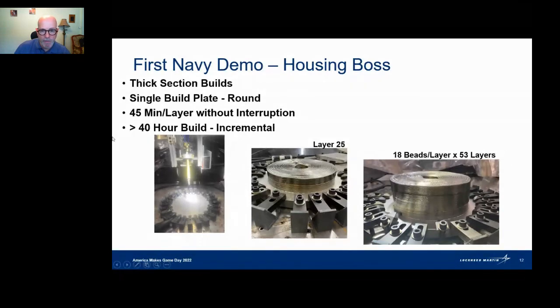The image that you see right here is when we'd gotten up to layer 25, and in the final image you can see it's 53 layers at 18 beads per layer. The essence here was being able to not only control the process, but predict what the thermal conditions would be as we conducted that build.